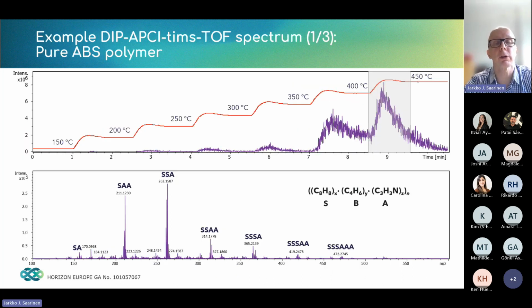Here's an example of the pure ABS polymer. On the top image, we have the typical total ion count spectrum that we gain from the measurement using the temperature ramp from 150 to 450 C. At the bottom image, we have the mass spectra at 450 C, and what we see from the ABS. We do see that there is a combination of different constituent components of the ABS: a styrene component, a butadiene component, an acrylonitrile component, and different mixtures of them. Here we see the SA, SAA, and SSA combinations, and all others as well. This is a very typical spectrum that we get from a polymer sample.